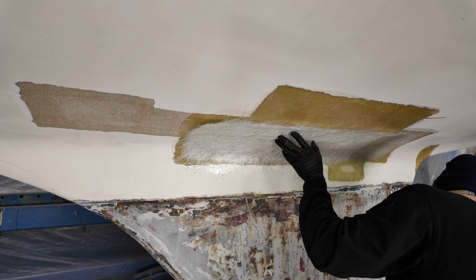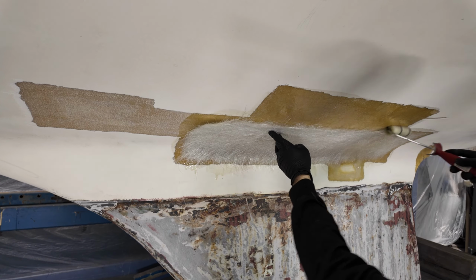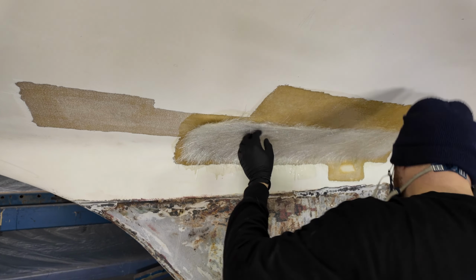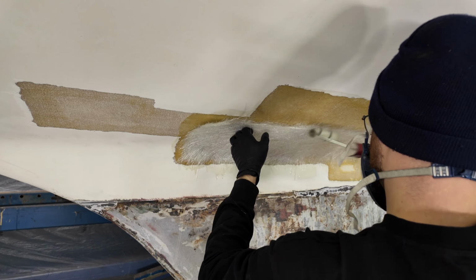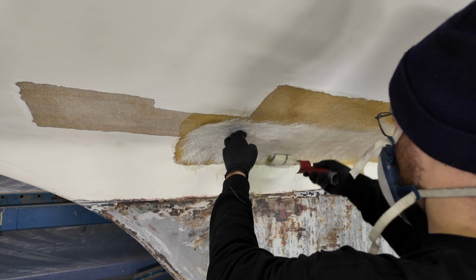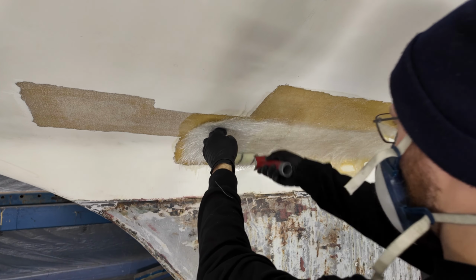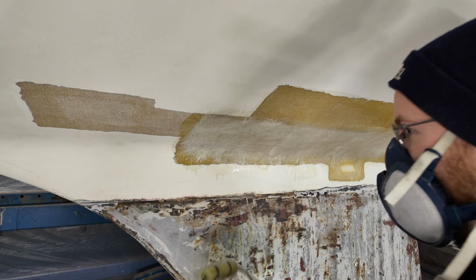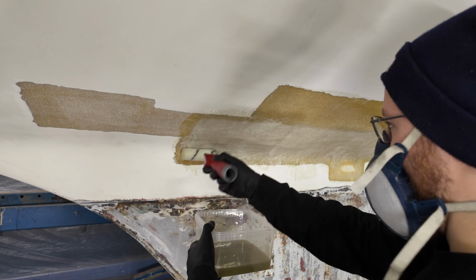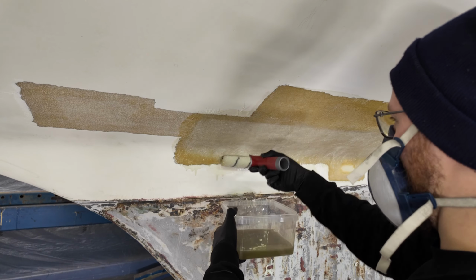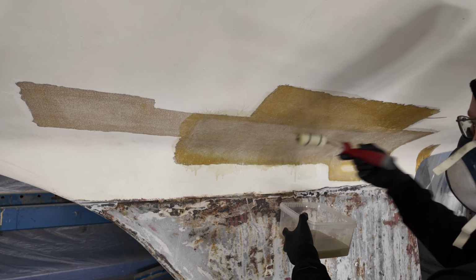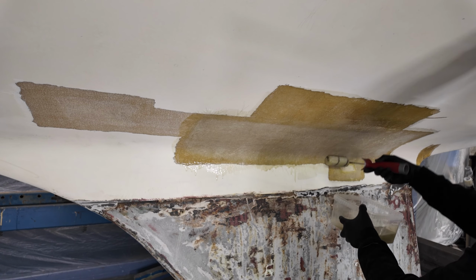Third, I find the woven fiberglass to be sometimes difficult to properly de-air, and the ends of individual strands like to stick out when rolled. A layer of chopped mat on top helps with that. Lastly, just 3 layers will probably be enough, because I didn't remove as much material as I originally imagined, and I will reinforce this area from the inside as well.